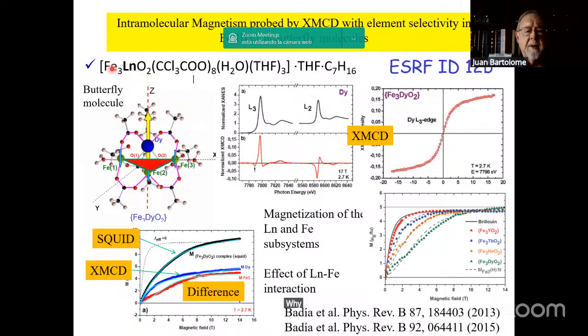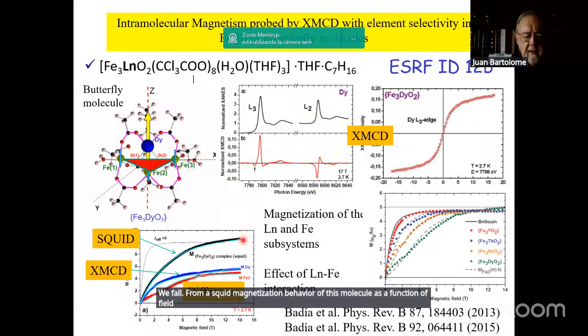Why butterfly? Well, the three atoms, which are iron-3, are in a triangle, and vertical to it, in the so-called body of the butterfly, is located the lanthanide atom. The rest of the molecule provides the wings of the butterfly. So we measured its magnetic behavior, and I'm showing here the case of dysprosium substitution. We found from a SQUID the magnetization behavior of this molecule as a function of field up to 14 Tesla. And then we were interested in understanding the interaction between the lanthanide and the iron sublattice.